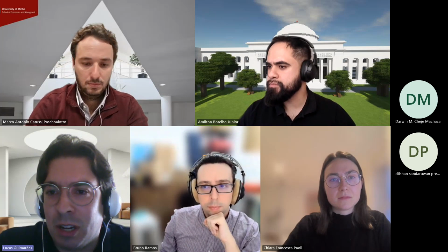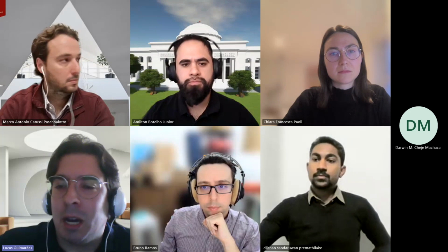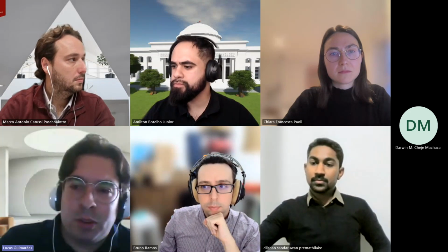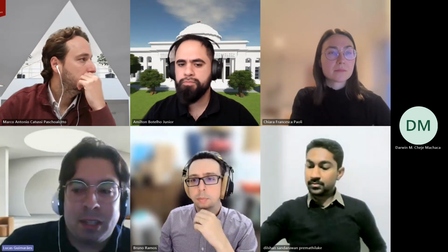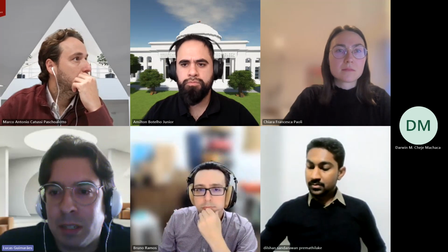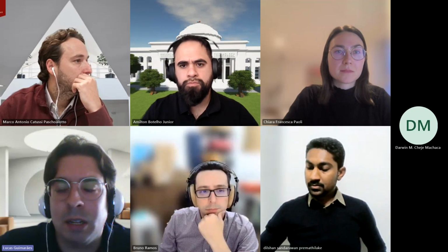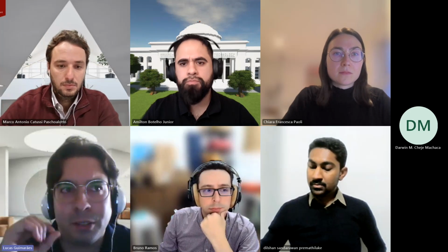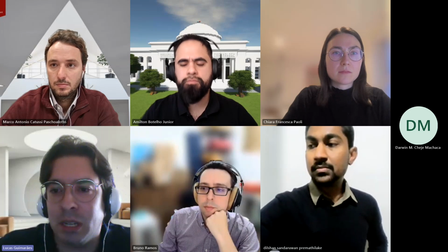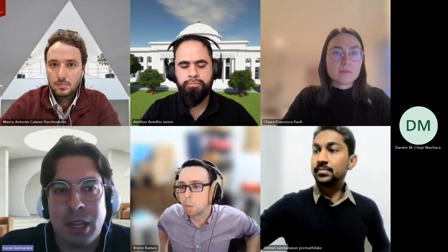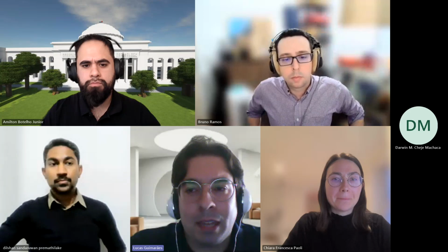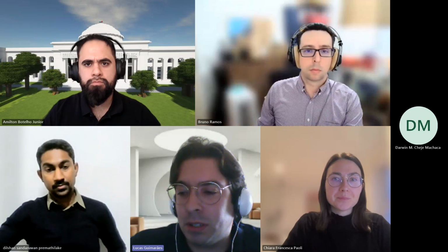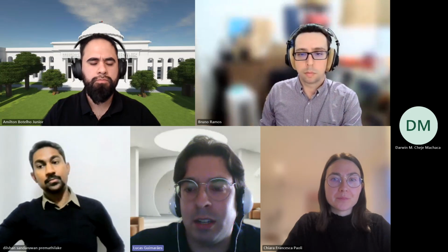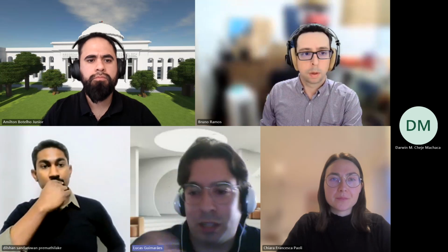Thanks for the questions. Very good questions, by the way. The first one, about the presence of copper in the black mass. Yes, I had some copper in the black mass. The great majority, as I said, could be removed during the pre-treatment, but still small pieces of metallic copper and metallic aluminum were present in the black mass. And at the best condition of the leaching with sulfuric acid, copper was not leached.